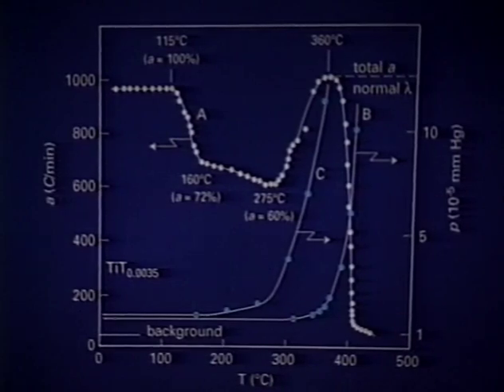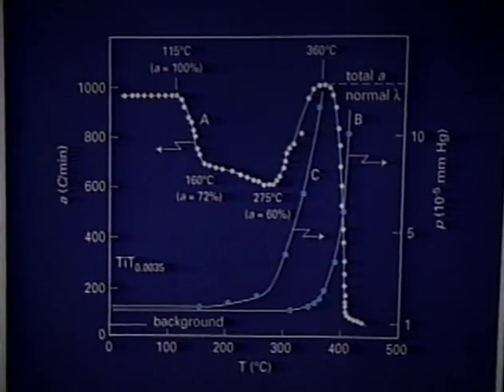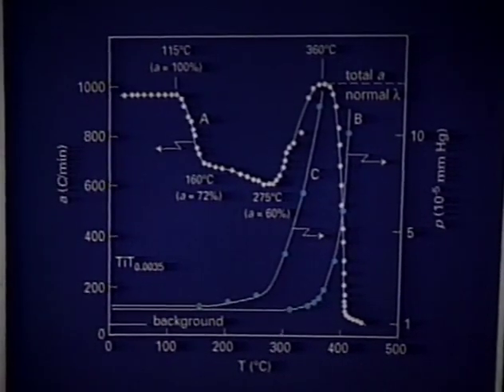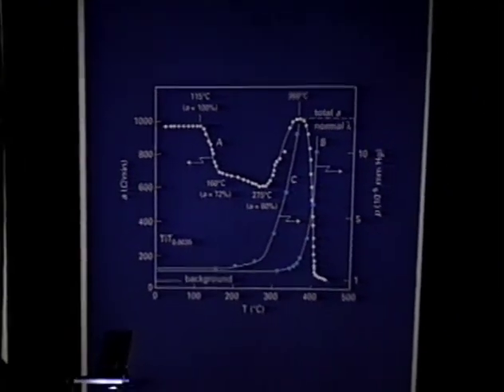And when the temperature was high, the oxygen atoms diffuse into the bulk of the titanium particles, so that a clean surface of the titanium particles is obtained. Then, at the second rise of temperature, the tritium atoms which are released from their bonds to the titanium lattice can immediately leave the small titanium particles.